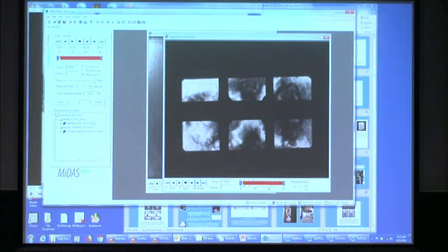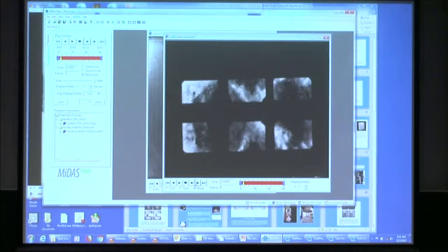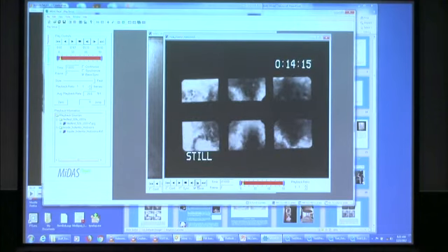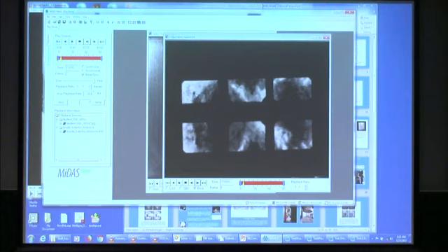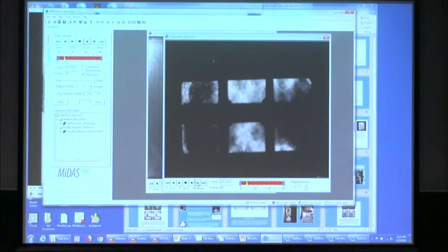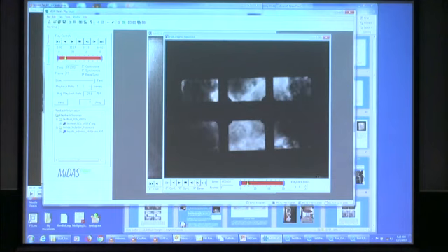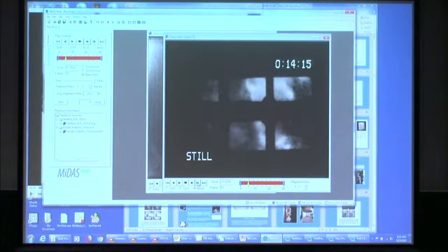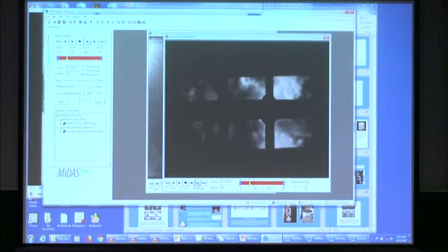So as this proceeds along, you can see new spalls popping in. So on the left here, you see that spall? So a big spall has just come in on the left. And as this proceeds, the material that was created by the spall moves away from the hard zone area. So spalls form, material's crushed, and then it just is squished out of the action area. So this just keeps happening.